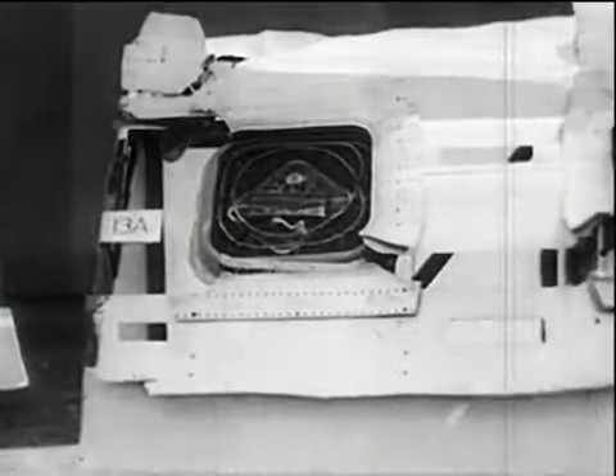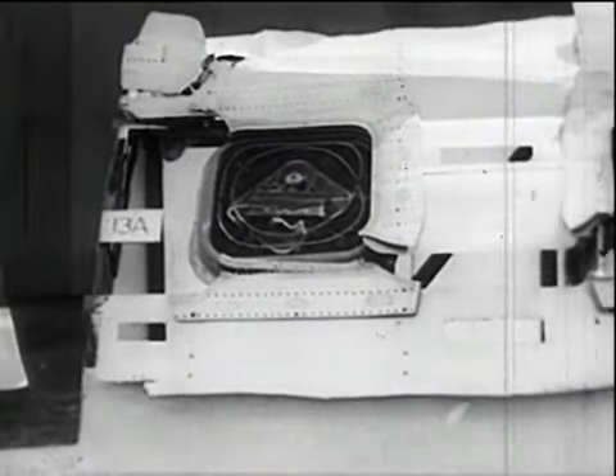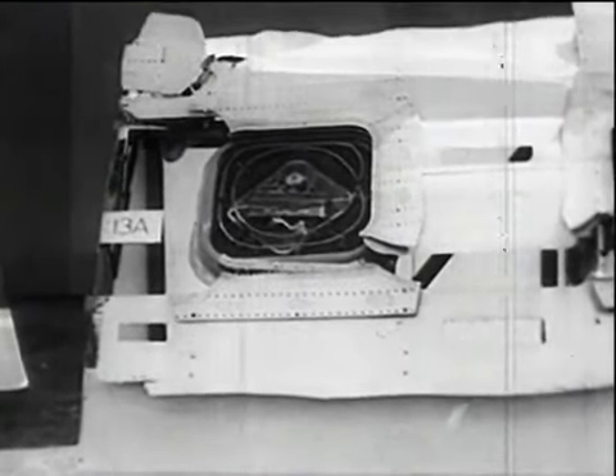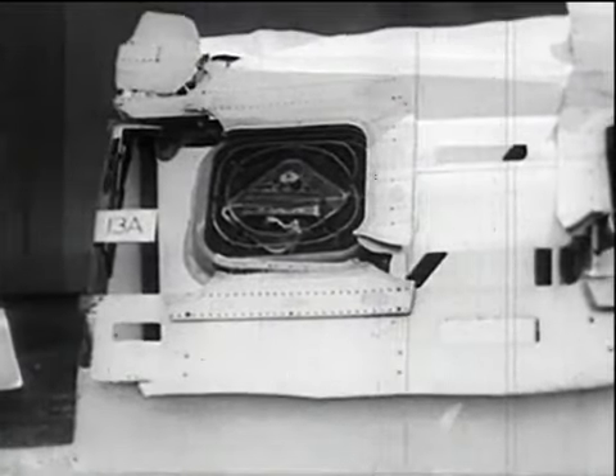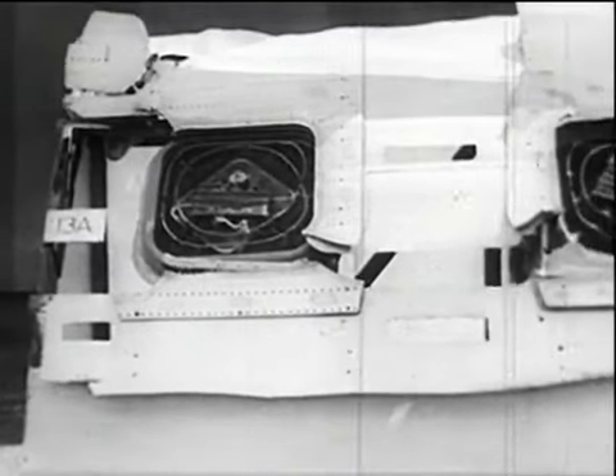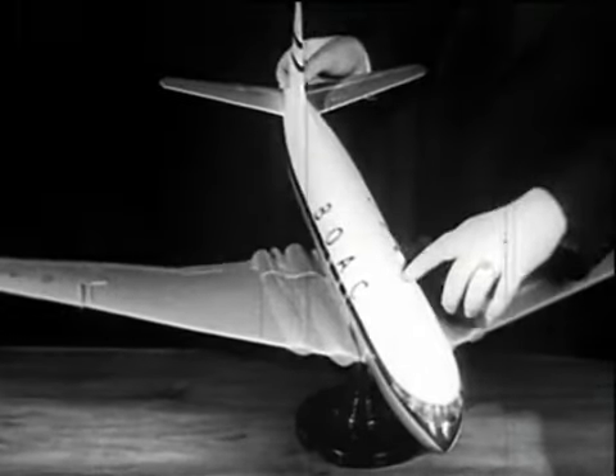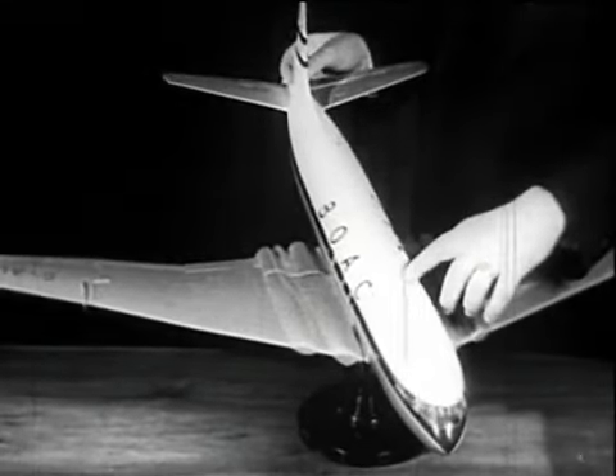The examination of the Elba wreckage, which had proceeded simultaneously with the fatigue tests, indicated that failure started at a direction-finding aerial window in the roof of the cabin. There were 2 of these windows, and the failures originated from the rear one.